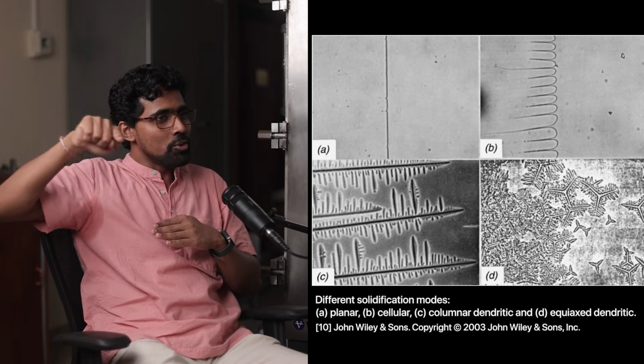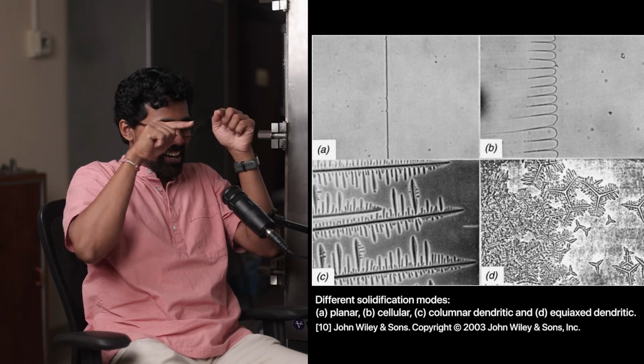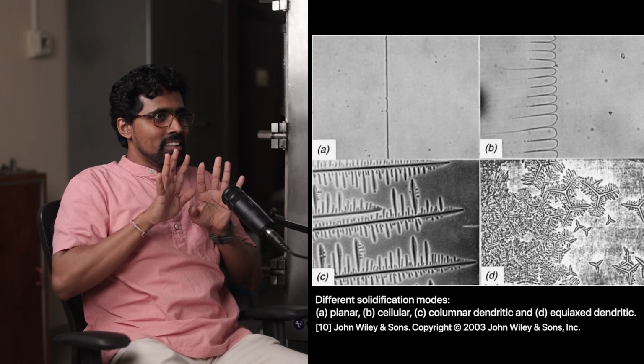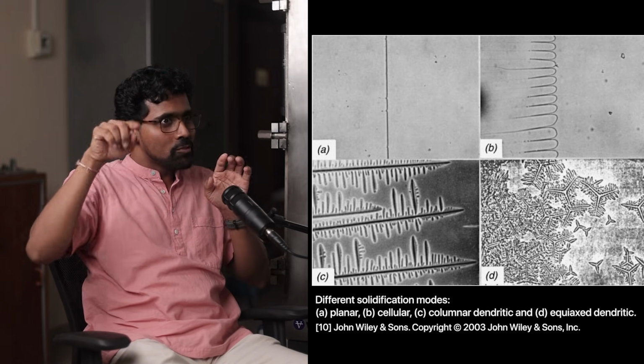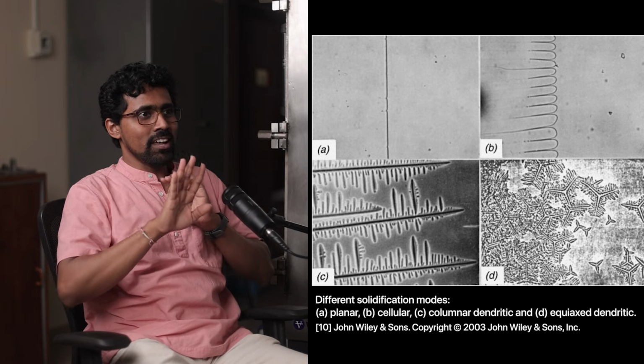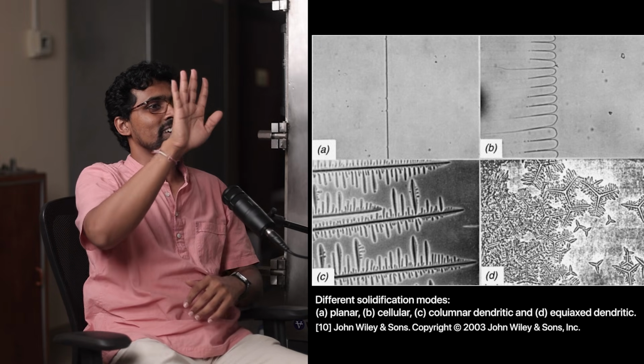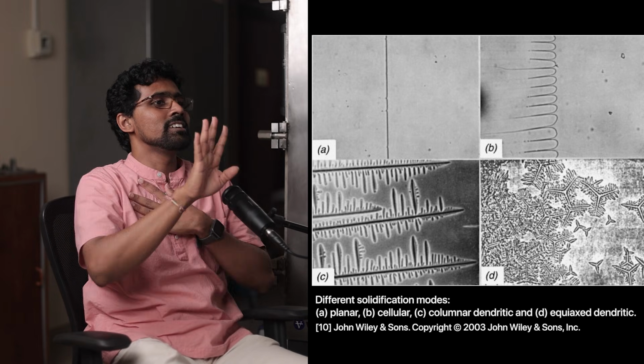Because we are solidifying at a certain rate, and if that rate is above the threshold rate, the interface between solid and liquid will not move as a plane. There will be some waves that form at the solid-liquid interface. Some of those waves grow, and what you would see are something like fingers growing. Yes, and those are called dendrites.